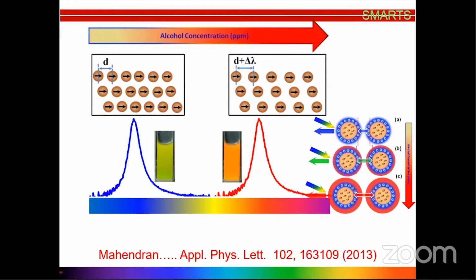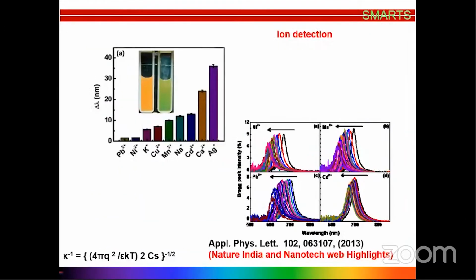And if you convert this shift delta lambda, you calibrate it, and you would be able to see what the concentration of ions is. Here again, you have an issue, which is the specificity. Obviously, you have to use molecules that are specific to a cation so that you will be able to get selectivity also. This is what we are working on. This is work done by a student, Mahendran, and he has done a lot of work to look at the sensitivity of these nano emulsions for detection of different cations, and he could achieve different levels of sensitivity by using different functional moieties. So one of the issues here is achieving 100% selectivity.